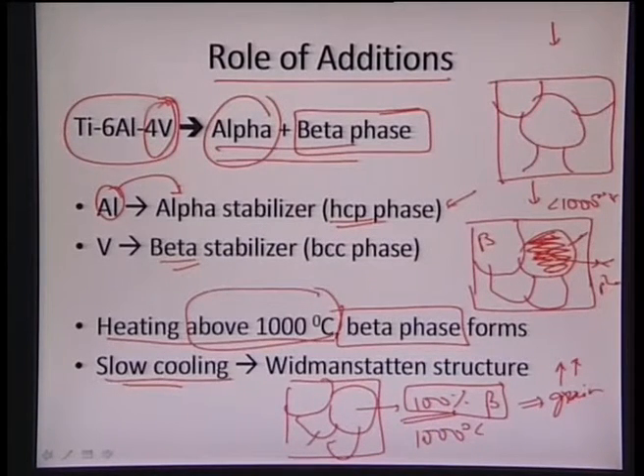Why? Because it can be very highly brittle, and this because its grain size is very huge, and also it is more like a needle structure. So needle, it means it can induce very high stress concentration factor. So that is the reason this structure is not so preferable. So we see very huge beta grains, and in those, once we start cooling it very slowly to lesser than 1000 degrees centigrade, we see that the alpha grains, which are HCP, they start precipitating, and since it is a needle like structure, this structure can induce very high stress concentration factor near its tip, because it's a needle like structure. So that is the reason it can be very deleterious.